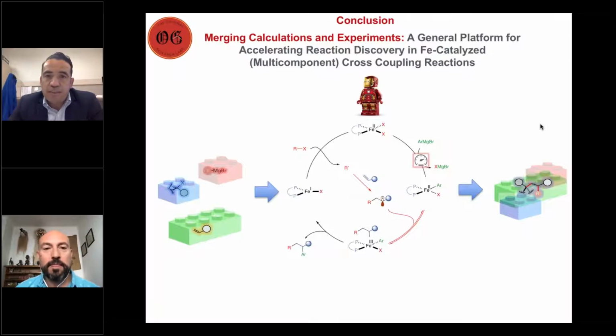So one thing that I will mention is that we tried a series of different pre-catalysts, and you can engage iron 2s and iron 3s, basically iron ACAC, and the yields change slightly, but they don't have drastic effects. So those do work. For simplicity, we just decided to go with the ones that gave you the best yields. But in reality, the pre-catalyst doesn't have so much of an effect in terms of the efficiency of these transformations. But we do see that what they have a drastic effect on is actually selectivity.